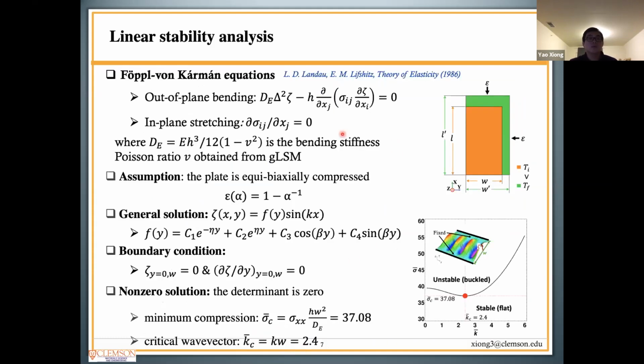In order to understand the fully developed patterns in confined hydrogels, we performed a linear stability analysis using the Föppl-von Kármán equations, which have two components. Here, D is the bending stiffness of the hydrogel plate, E is Young's modulus, and ν is the Poisson's ratio of the hydrogel, which can be achieved by GLSM simulations. Zeta is the out-of-plane displacement, which describes the surface topology. Due to the balance between the thermal stress and the compression, the gel plate is assumed to be flat but actually compressed. So we can relate the strain to the alpha. Solving the Föppl-von Kármán equations, we can get the predictions of both the minimum compression for pattern formation in confined gels and the corresponding wave vectors.